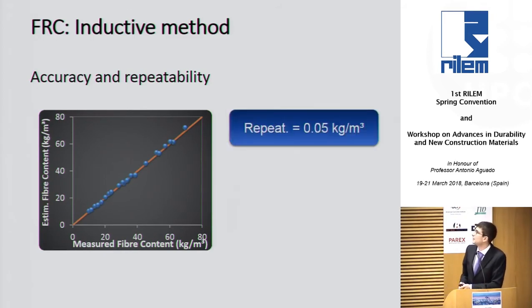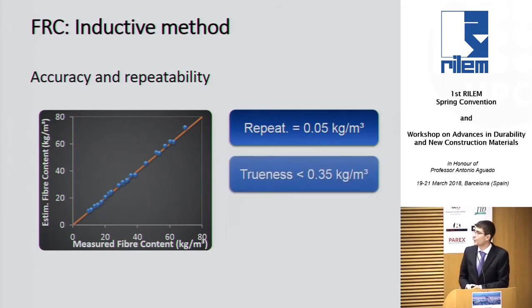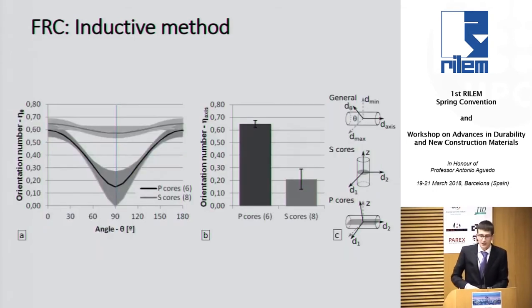Right, so we have a repeatability of 0.05 kilos per cubic meter of fiber, in typical steel fiber, and a trueness of 0.35 kilos per cubic meter, which is very good, right, for the measurement, considering that we are typically talking about contents above 20 kilos. One of the things that we've done with this is to measure, for instance, the fiber distribution in sprayed material. It was a study that we published recently.